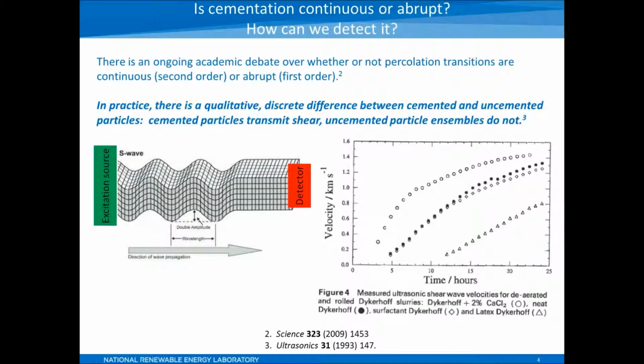The figure on the right shows essentially shear wave sound velocity in a whole bunch of different types of cements as they have cured. The x-axis on that graph is simply time after the slurry has been mixed together. That's from the ultrasonics paper from '93. If you pick any one of these curves, you'll see that at low curing times, the sound velocity has dropped to 0. Essentially, it's not defined. The shear waves are not propagating in this wet slurry. And then at some point, there's a well-defined shear modulus that allows the shear waves to propagate through the material.